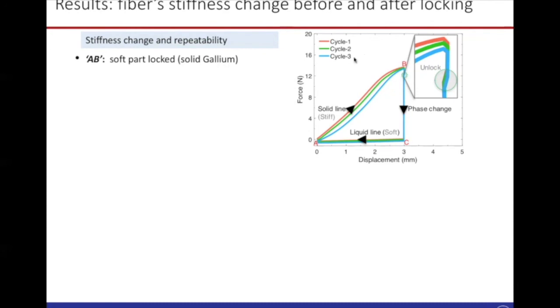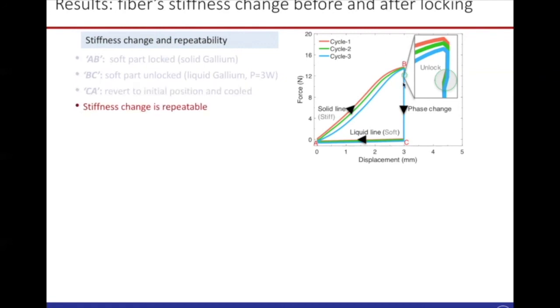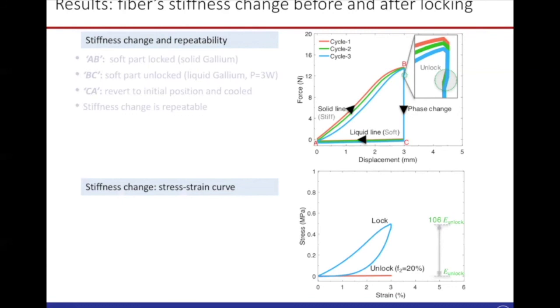The gallium switches from solid to liquid, and you unlock the soft part, and then the force dropped and reduced drastically, indicating that the stiffness of the fiber changed. Then we reverted this fiber back to its initial position, and the gallium is allowed to cool to regain the stiffness, and the test is repeated. The result shows that the stiffness change is repeatable.